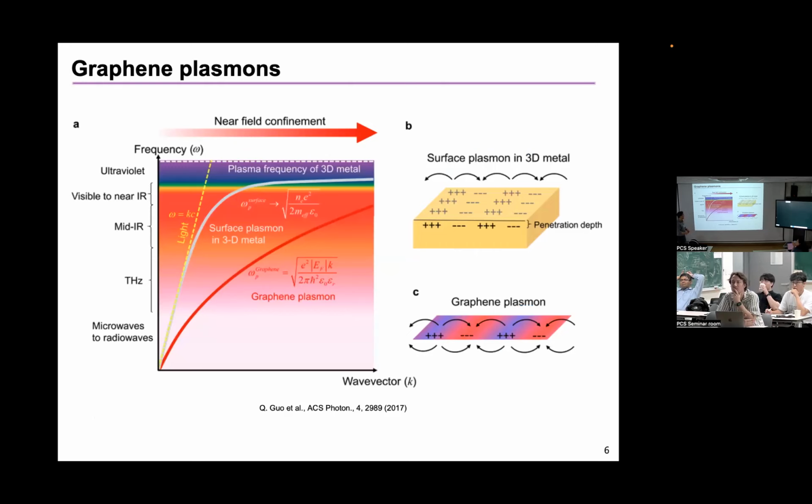Surface plasmons are generated at the interface between a dielectric and a metallic structure. These two permittivity values should have opposite signs, positive and negative. Based on this condition, the surface plasmons can be generated at the interface, right? So it's very important to have some bulk connected to the two-dimensional interface. Yeah, but in that case, the graphene or metal structure should be a conductive, metallic material.